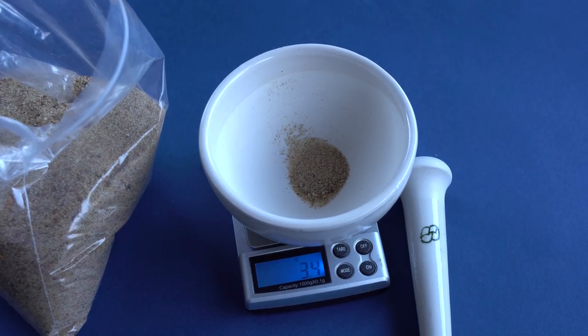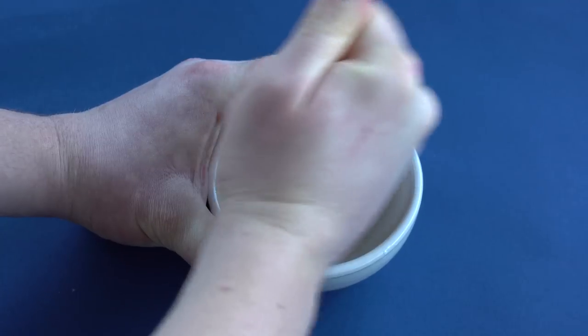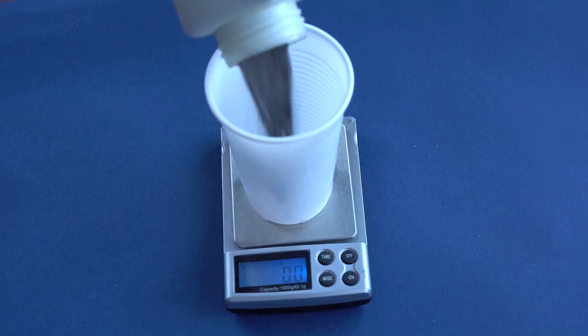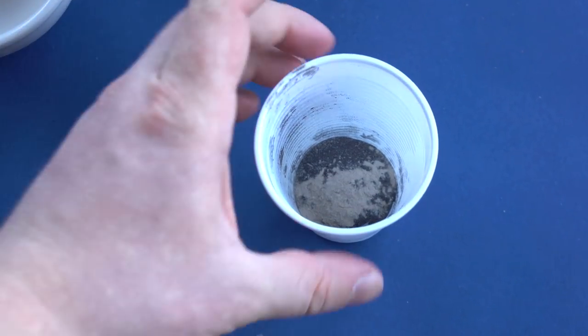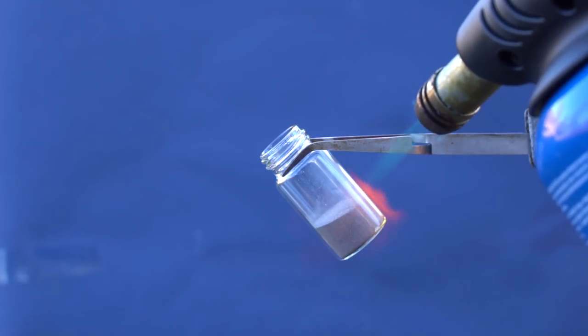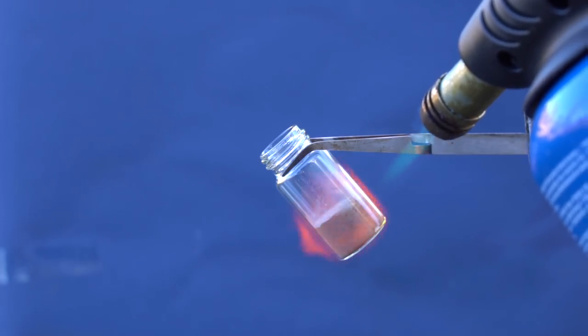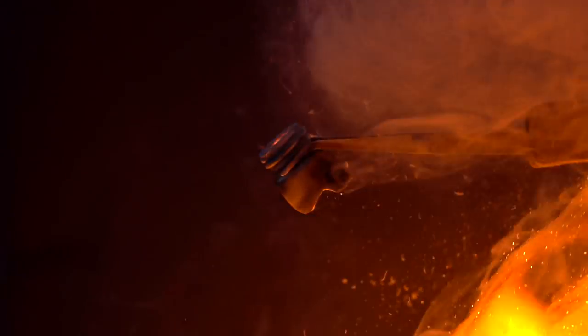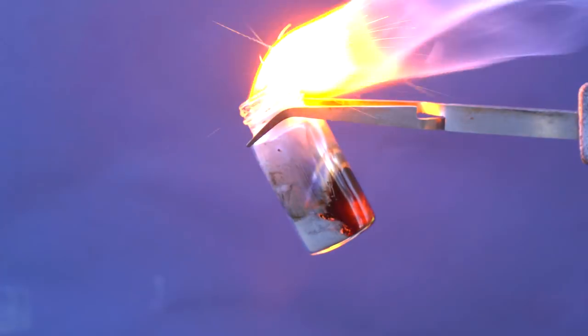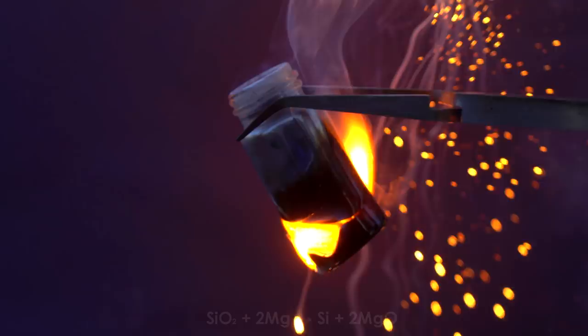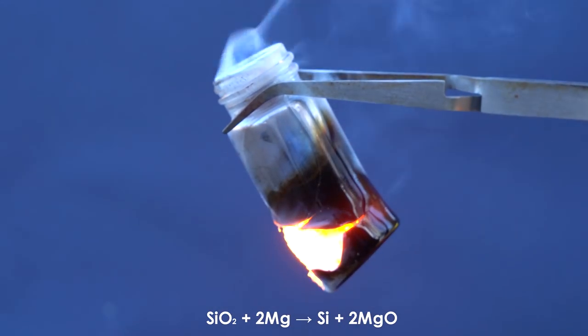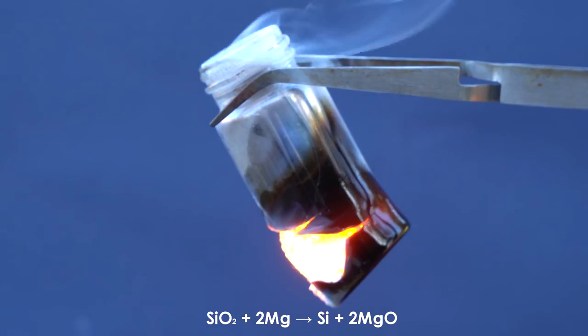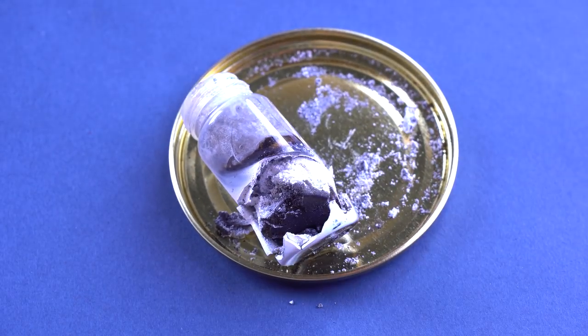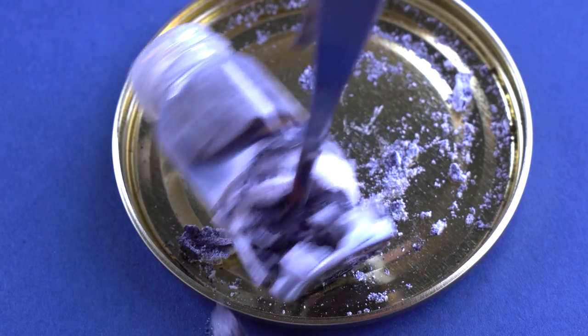I'll also try to obtain amorphous silicon, but I'm going to resort to another method. I'm going to mix 1/10 of a mole of magnesium and 0.05 of a mole of fine sand. First, I decided to run this reaction in a glass tube. However, because of the rapid heating up of the mixture, the glass cracked and its content poured out. Do not try this at home. When I heated up the mixture for the second time, it went much better and the content didn't pour out. In this reaction, metallic magnesium reduces silicon dioxide to silicon, forming so-called amorphous silicon, which looks like a black sponge.